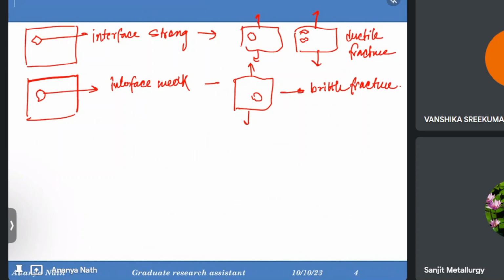The fractographic images were shown at the time of class. Those images are not with me, but if you remember, there will be some dimples created in the case of ductile fracture. This type of holes will be created. These are basically due to the fatigue testing or just the tensile compressive testing, and the particles got separated from the holes. This was the hole previously where the particles were seated, but now the particles are separated from the matrix, so these are empty holes. You will see this type of features in a metal matrix composite when you expose it to fatigue fracture. The yielding of the matrix at the broken edges will relax the stresses and will prevent the crack from propagating. The result of which is the blunting of the crack tip.